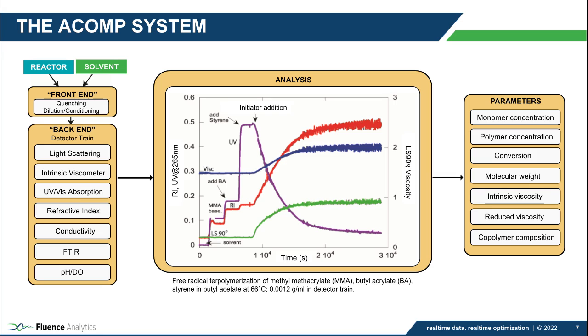application needs and have a variety of detectors such as ultraviolet visible spectrometer, light scattering, viscometer, refractive index detector, conductivity meter, infrared spectrometer, etc. All this raw data is collected throughout the reaction, as can be seen on the plot in the middle, and based on some reference values, solvent and monomer baselines, many parameters are automatically calculated, such as monomer and polymer concentrations, conversion, cumulative and instantaneous molecular weight, intrinsic and reduced viscosity, and copolymer composition. These parameters are responsible for the final polymer material properties, such as strength, brittleness, melt temperature, solubility, etc. Therefore, monitoring polymer properties during synthesis is the first step towards achieving control of the production of tailored polymers.